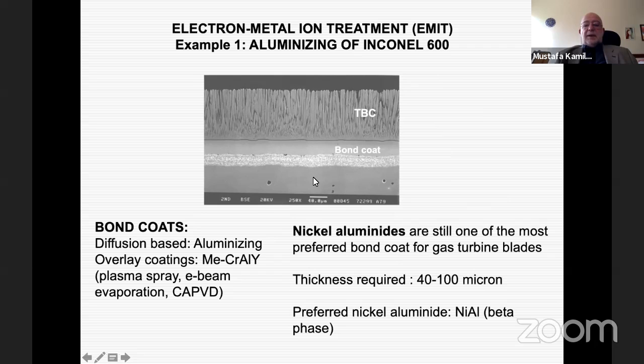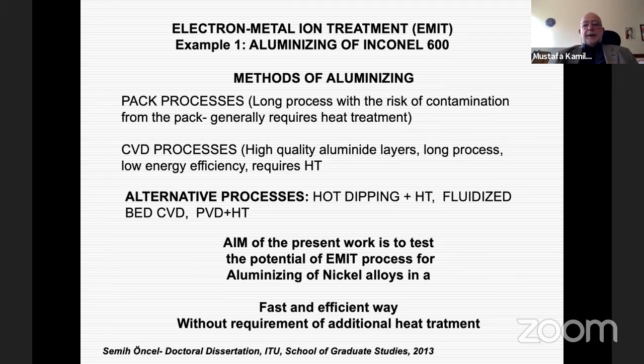or cathodic arc PVD. So another application, in this case, is aluminizing the surface of the nickel alloy to form a diffusion-based layer mainly composed of nickel aluminides. The thickness required for this purpose is about 40 to 100 micrometers, and the preferred phase is nickel aluminum phase. As I said, there are lots of processes for aluminizing these materials, pack processes, CVD processes. I'm not going to go into details.